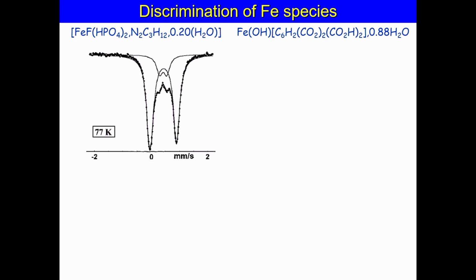So we have one sample on the left side. The student came to me and said, I have one structure with a single iron site. Okay, we do some spectrum, but the spectrum consists of two doublets. Two doublets means two different iron sites. Why? I don't know. So I made complementary measurements to convince her that she was not right. After a few weeks, she came to me and said that by analyzing the Fourier map by X-ray diffraction, maybe there are some water molecules.